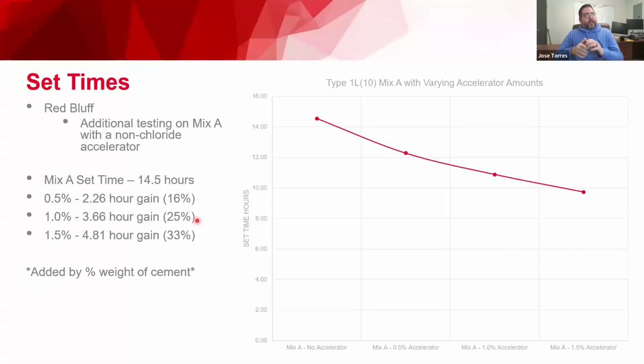In the end, we did not use it full time at Red Bluff, only because we get 120-degree weather all the time, and we're using chillers and all sorts of things to keep our mix cool. Using accelerators in those kinds of conditions could get dicey if things break down. So we didn't opt to use it, but this is good news for those of us looking to get that set time down.